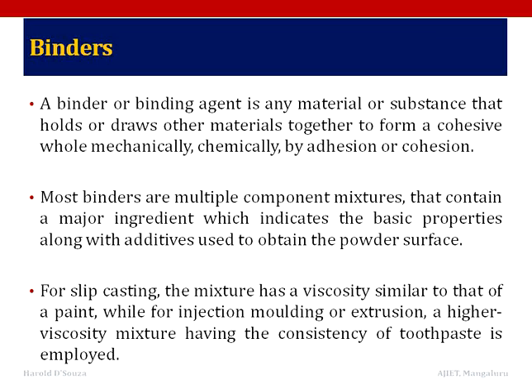For slip casting, the mixture has a viscosity similar to that of a paint, while for injection molding or extrusion, a higher viscosity mixture having the consistency of a toothpaste is employed. Now, the attributes of a binder include toxicity, cost, flow, and ease of manufacturing. The other important requirements of a binder include easy removal prior to sintering with minimum contamination and little or no interaction with the powder or ambient environment so as to prevent property changes over time. Now, generally, the binders are either thermoplastics or water based gelatin systems.